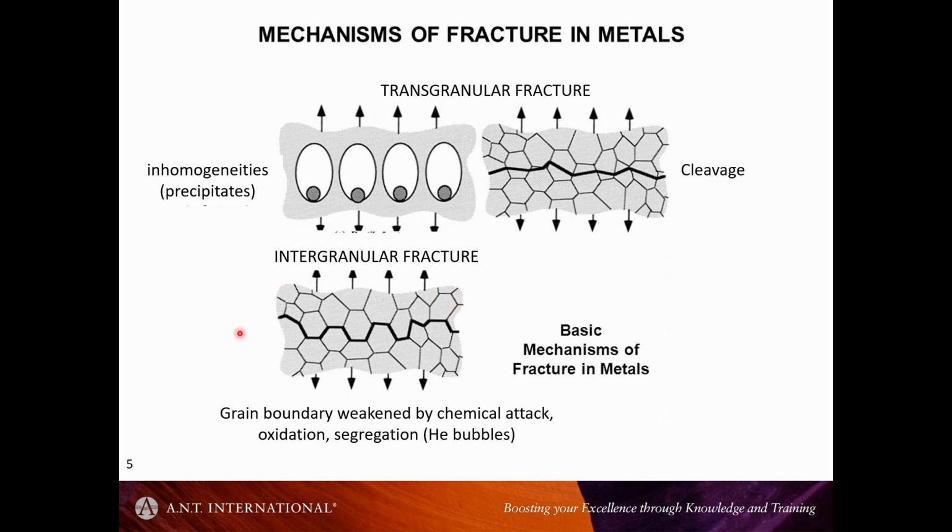And then the other mechanism of interest is this intergranular fracture. And typically, this applies when the grain boundary is weakened, either by chemical attack, oxidation, or segregation. In this particular case, I'm thinking about helium bubbles, and that becomes very important when it comes to reactor materials.